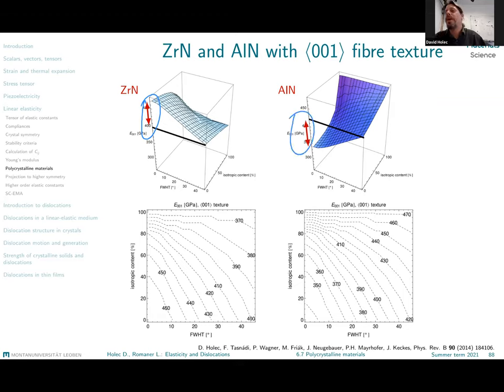The same thing is true here for aluminium nitride. Again, from 330 up to 420. Right? So a huge spread of values. All of them calculated from single crystalline values, the same and identical single crystalline values for either zirconium nitride or aluminium nitride. But this huge dependence is simply related to the texture that you have in the material. So we need to wait for loading the figure and then we can move on.